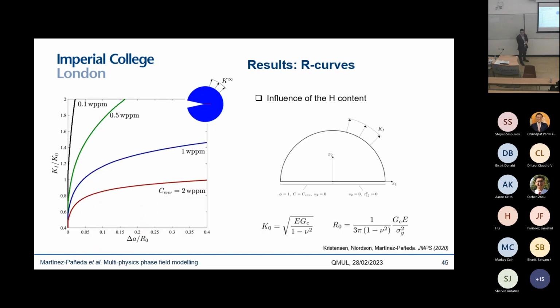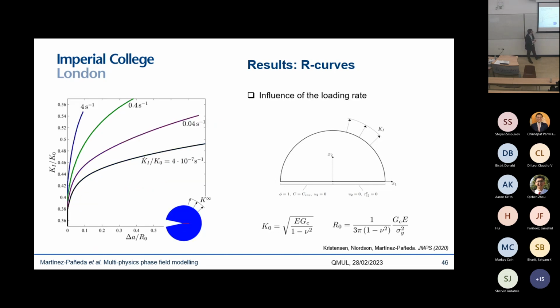So these are R curves, crack growth resistance curves. So the y-axis is a measure of the applied load, or the crack tip stress condition, and this is the crack extension. And you can see that we get what we expect from the experiment. So as you increase the hydrogen concentration, you lower the crack growth resistance. Another interesting effect is the sensitivity to the loading rate. So again, we see what you see in the experiments. If you load very fast, there's not enough time for the hydrogen to accumulate in the fracture region. As a result, you gain some fracture resistance. But if you load very slowly, then you leave enough time for the hydrogen to accumulate in these critical areas, and you reduce your fracture resistance.